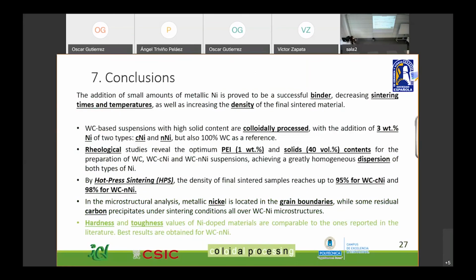In the microstructure analysis, metallic nickel is located, as we appreciated on the micrographs, all over the grain boundaries, while some residual carbon precipitates under sintering conditions all over the microstructure. And finally, both hardness and toughness values of nickel-doped materials are actually comparable to the ones reported in the literature, but the best results were again obtained for tungsten carbide with nanonickel.